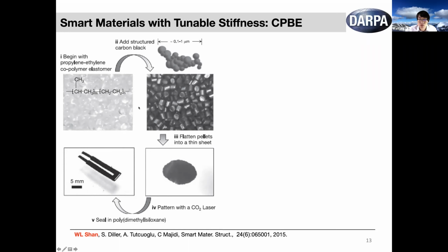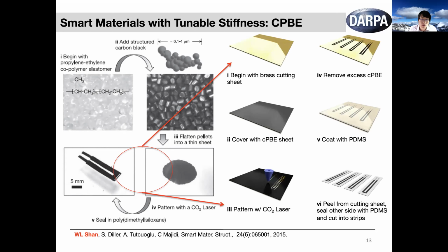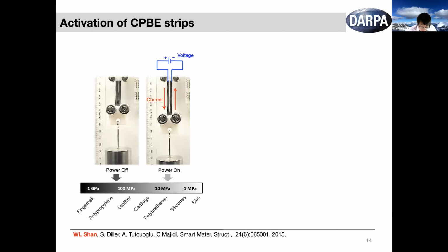So basically, for this smart material, we start with propylene-ethylene copolymer elastomer, and then we add carbon black into the mix. We get this pellet form, and then because of the low melting point of the copolymer elastomer, we can easily machine it by applying heat and pressure. So we can use a heat press machine to laminate these pellets into thin film, and then use a laser engraver to pattern it into the structure that we desire. From step 4 to step 5, there's a multiple-step manufacturing process, which I won't elaborate on here. This slide is some characterization of these CPBE strips.